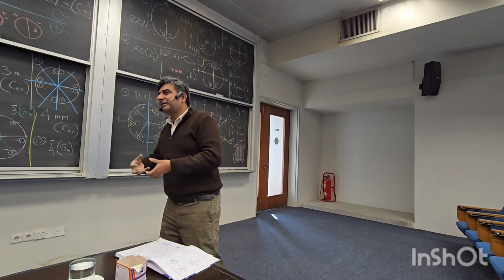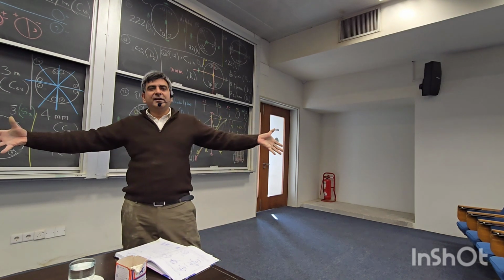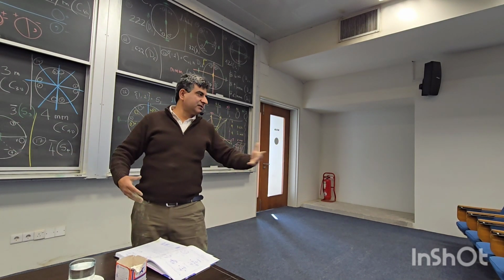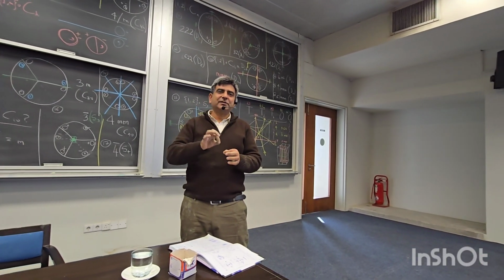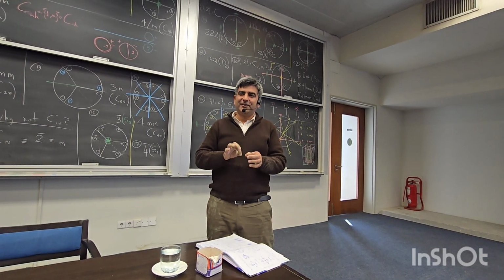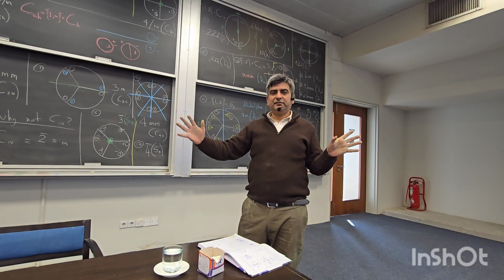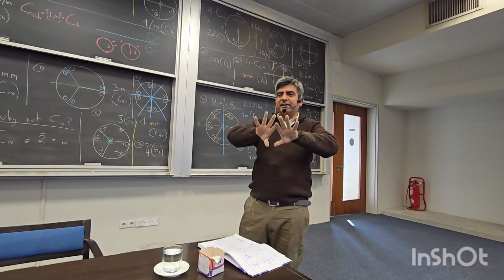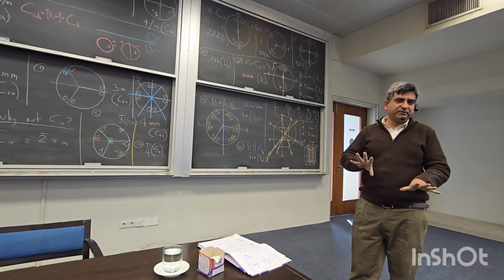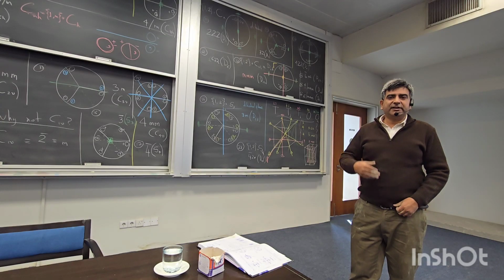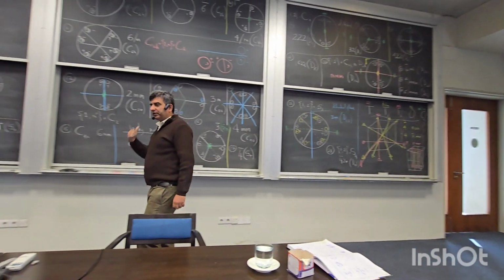The unit cell is a replicated unit inside the lattice. You have one unit cell, you know what the entire lattice is going to look like. Just repeat it by translations. And then you put face-centering on those different faces inside those 7 crystal systems to get the 14 Bravais lattices. Okay, so this is the entire glory of crystalline structure coming in front of you. Okay, so in the next lecture we're going to look at the 7 crystal systems and how they come out from the point group point of view.